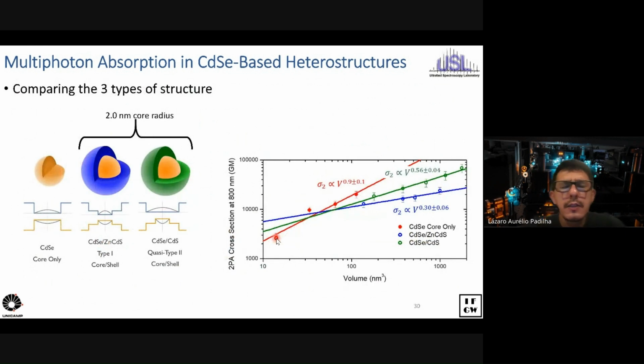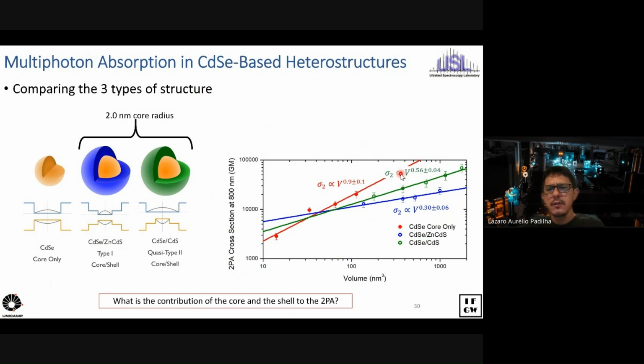So you're not favoring the increasing of your two-photon absorption cross-section. So what about the quasi-type 2? When you do it for the quasi-type 2, we see a very interesting result because it actually falls in between the type 1 and the core only. And to rationalize this, we need to think about how the electron and holes interact in these materials. But before that, the question I ask is, what's really the influence of the shell on this whole process?